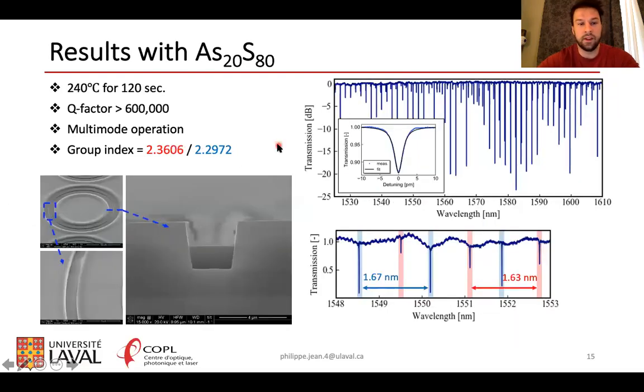So next, the optical characterization of microresonators made with As20S80. For these, we did dewetting at 240 degrees C for 2 minutes, and we saw a small improvement in Q factor with a value just over 600,000, which is about 0.7 dB per centimeter. And again, the waveguides here were multimode, and we measured group indices of 2.36 and right around 2.3, which is a bit smaller than for As2S3, as expected.